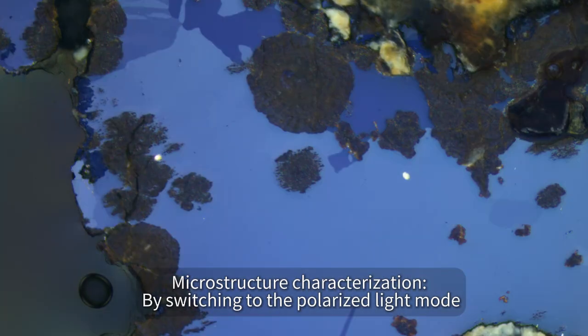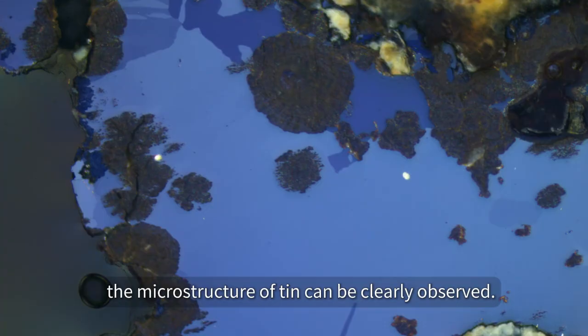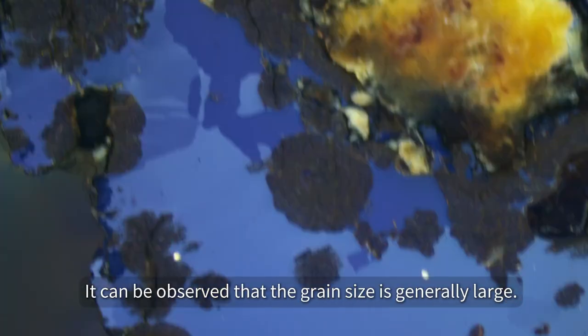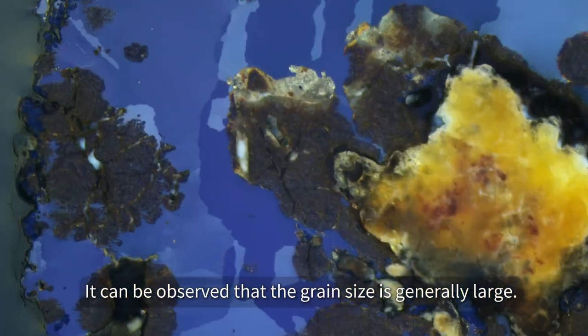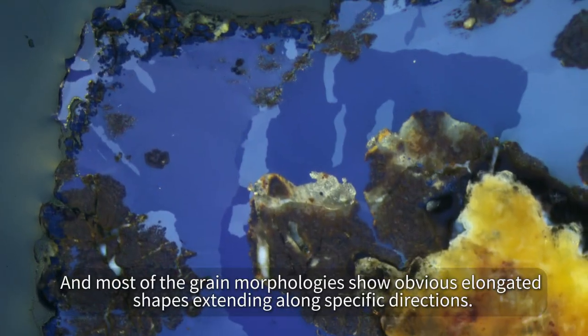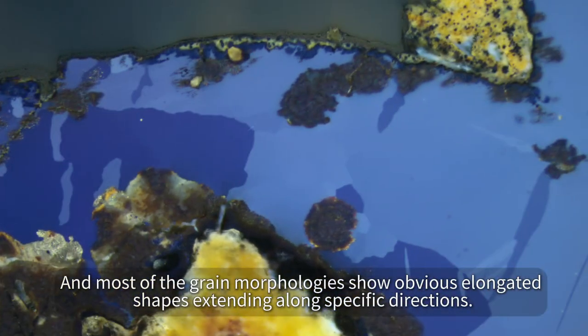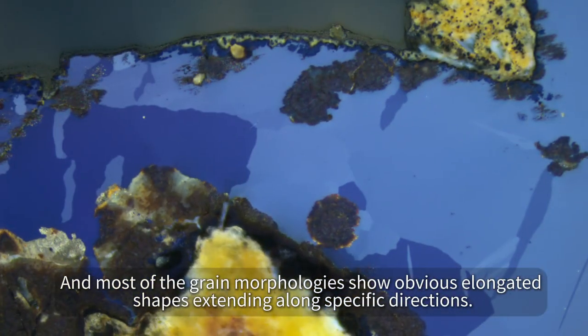Microstructure characterization. By switching to the polarized light mode, the microstructure of tin can be clearly observed. It can be observed that the grain size is generally large, and most of the grain morphologies show obvious elongated shapes extending along specific directions.